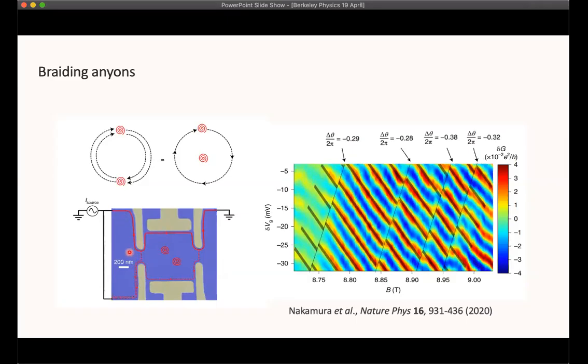And they built themselves a small Fabry-Perot interferometer. And so you can see that at these pinch-off points, they built a sort of quantum point contact. And the current that flows around the edges, some of it can backscatter and some of it can go through. And if you follow the path that the current takes, then you see that some current can travel all the way around and encircle this area inside the interferometer, whereas some of the paths do not encircle the area.